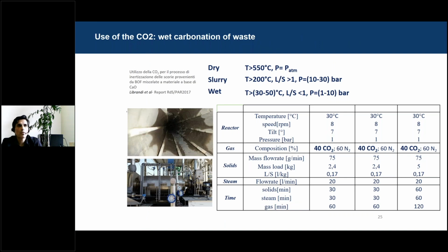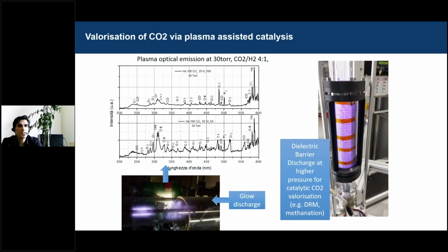Here, just for your information, I reported another experimental campaign regarding the use of calcium looping as a process for permanently storing CO2 in an alkaline industrial waste like steel slag, or even the ash from incinerators, because the ash from incinerators, like the steel slag, has a good alkaline component, which is able to be carbonated and so to be used as a storage of CO2. These are freshly baked results in the Zecomix,